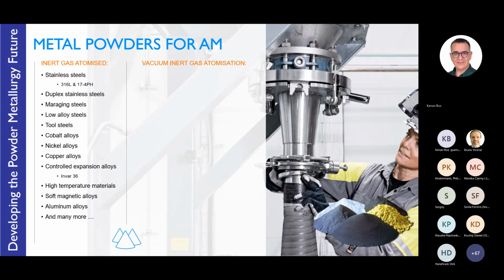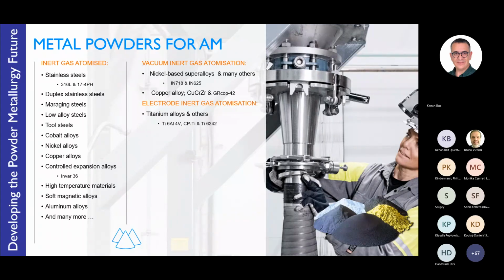And then we compare with vacuum inert gas atomizing, employing the process to manufacture nickel-based superalloys, so Inconels, as well as many more. And there is work going on to expand the range of nickel-based alloys. Copper alloys have also been applied, including copper chrome zirconium and alloys developed by NASA called GRCop-42. So these are copper chrome niobium alloys. So they're stable at high temperature, but still impart good thermal conductivity. Electrode inert gas atomizing typically produces titanium alloys.